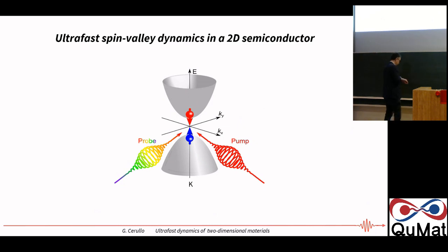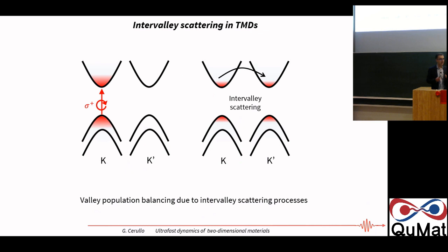Now I want to show you ultra-fast spin valley dynamics. So as I said, you can use circularly polarized light to selectively excite one valley. For example, we can excite the K valley. Now, what can happen is a so-called inter-valley scattering process. So you can have, of course, population equally distributing among these valleys. And we want to measure how long it takes for this process, so for how long the polarization remains in this valley.